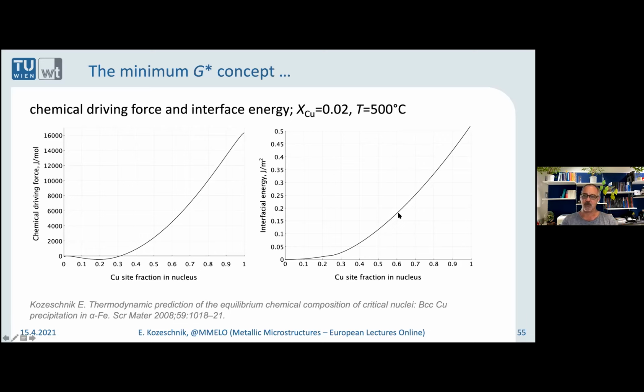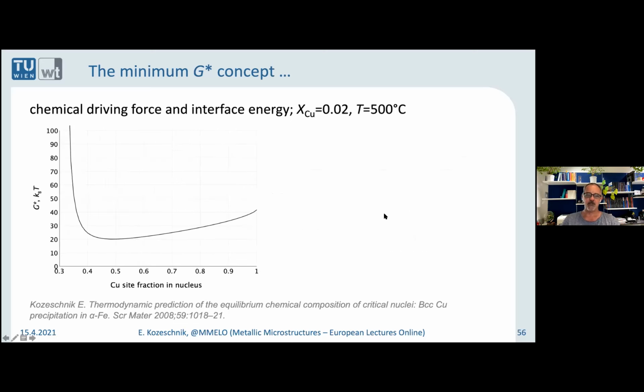When you have the two functions, you can put them into the equation and calculate the nucleation barrier, G star. And this is what comes out. This is the copper content. And you can see that the function has a minimum here in the proximity of half and half copper and iron.